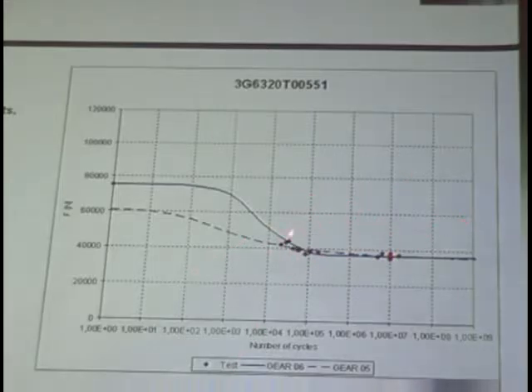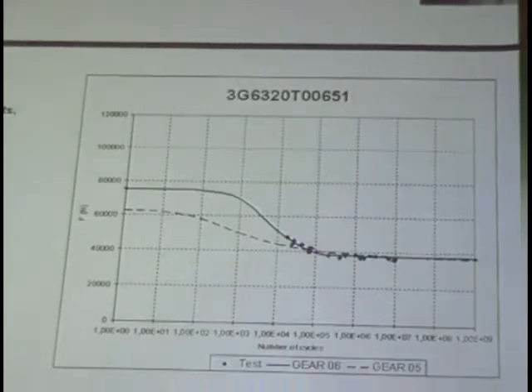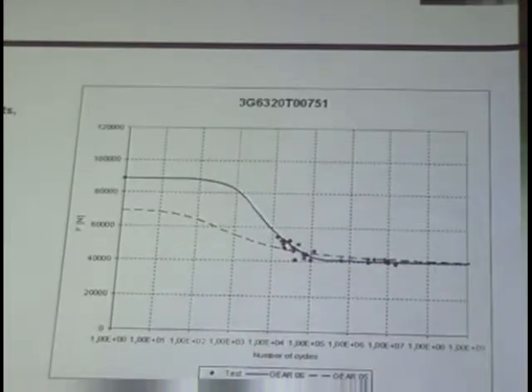And here you see that in this case, for the unground fillet, we had either failures below 10 power 6 or run out. We have a mixed behavior, so probably we will need to make some other tests in this region to confirm this data. And then this is without vacuum, so just the vacuum arc melted material, and this finally the Pyrowear or AX53 material.